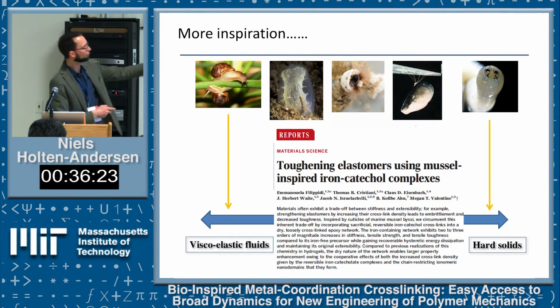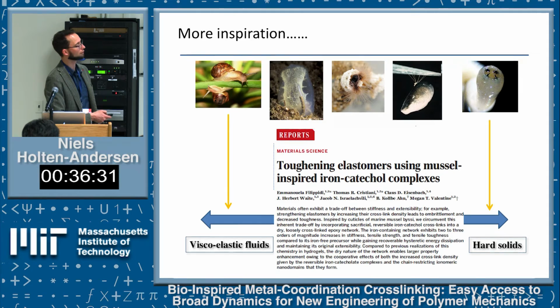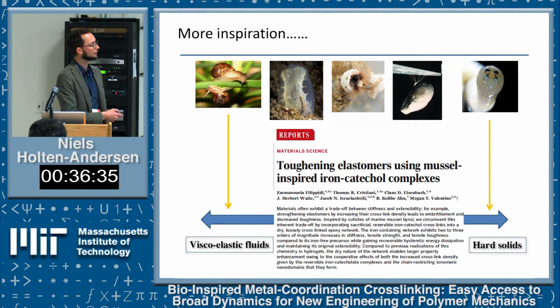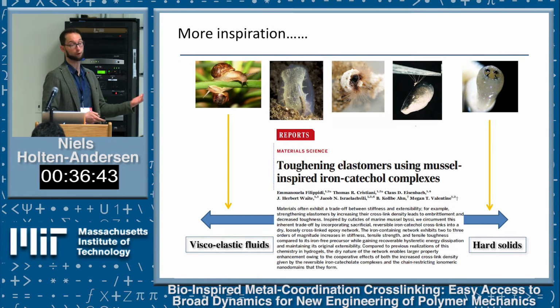This is just a shout out - we didn't publish this work, but some people at UCSB have begun using these mussel-inspired iron-catechol coordinate complexes in an elastomer, again with no solvent in the material. They report completely orders of magnitude more tough and stiff elastomeric properties than what's otherwise been seen with traditional chemistry. It definitely seems to be a useful cross-link chemistry.